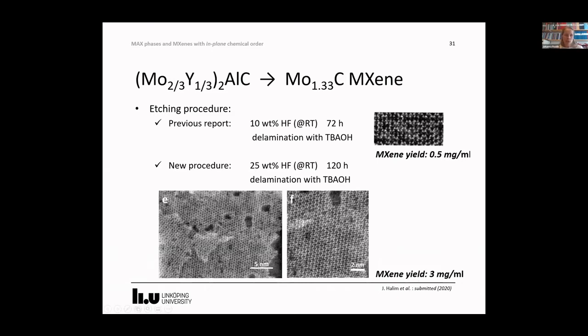And as important, if you look at this STEM image, you see the well-defined MXene of high structural quality with the ripples or chain-like features that are characteristic of the ordered vacancies. It should also be stressed that this yield, 3 milligram per milliliter, is 3 times higher than what we get from the scandium-based i-MAX phase.